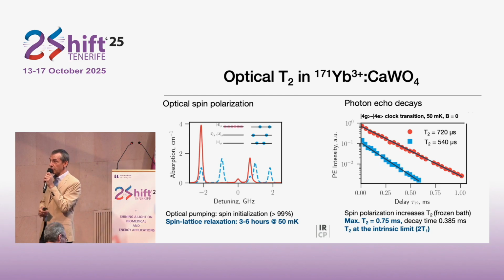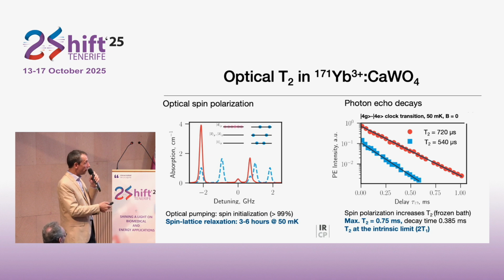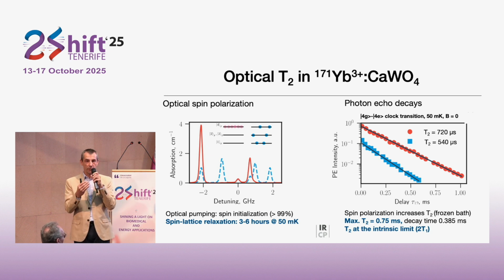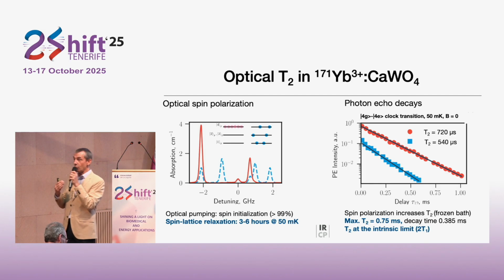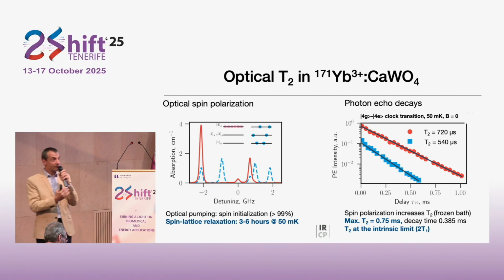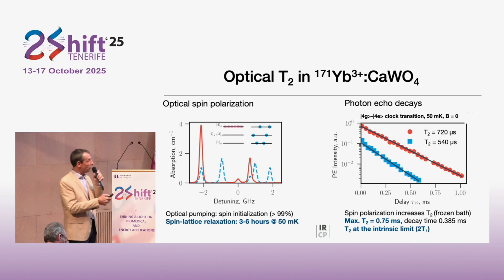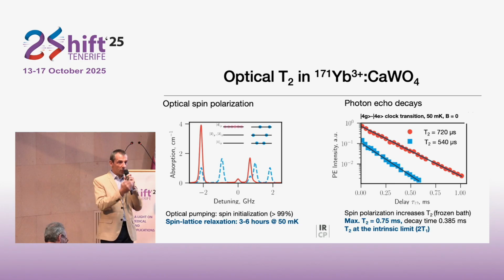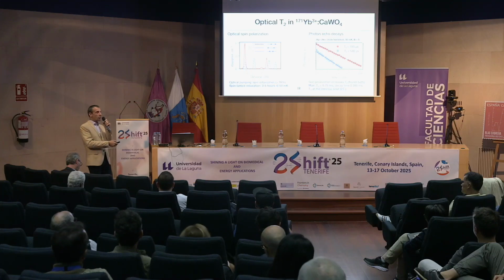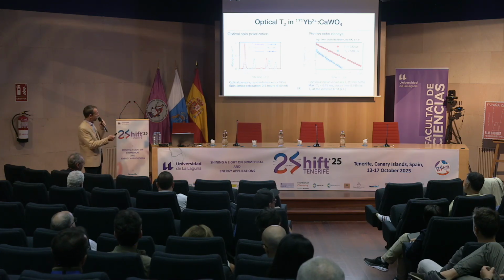And this is quite remarkable because there are very few rare-earth crystals where you can observe this limit. It means that all other perturbations are very small. So the only thing which is actually really interacting with ytterbium-171 in calcium tungstate is in fact the interaction with the vacuum field, its spontaneous emission. And so we have a system which is, on the one hand, very quiet, with very low perturbations, and the ion is also very well decoupled from the remaining perturbations. This is very important for quantum communication, because it is a very nice property if you want to do single photon emission, for example.